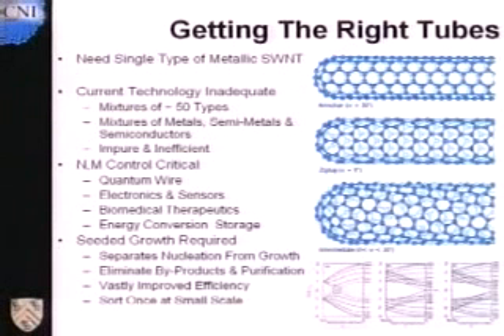And so the current technology we have for producing the nanotubes is relatively impure and relatively inefficient. So what we want to do is gain control over the N and the M. That'll open up a whole number of applications. The primary one here is the quantum wire. And so if you think about how to grow these things, now they're grown right now from a spontaneously nucleated nanometer size iron catalyst particle. And then after the cap forms, it's thought that then the tube starts growing, but it can pick any one of these stable configurations. Now, what we think the right approach here is to use a seed of an original nanotube as a template to grow more material, and thereby essentially grow from a nucleation and a predefined metal catalyst particle that you put on purpose.